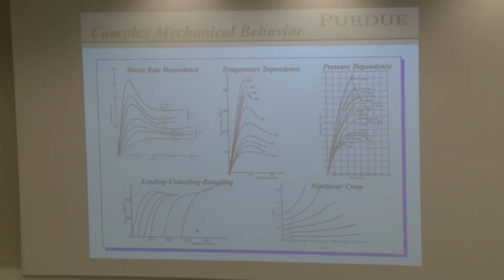Okay, now I showed you schematics before. This is a whole series of data. We see this stress-strain curve with that overshoot peak I showed you before, and notice that it depends upon, I can't even read what we have here. Those are two different temperatures and different strain rates. So it's very temperature and strain rate dependent. Here's the effect of temperature again. Notice we're talking about a 3 or 4-fold difference in the maximum the material goes through. This is the effect of pressure. This is the effect of stress, and we get nonlinear creep.